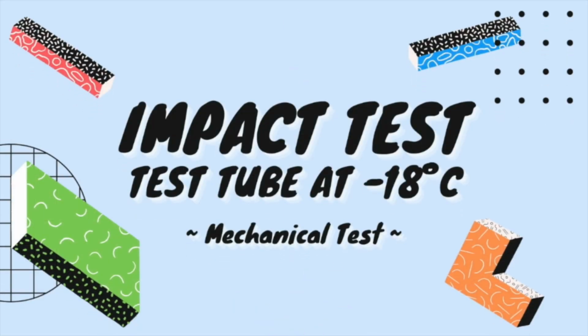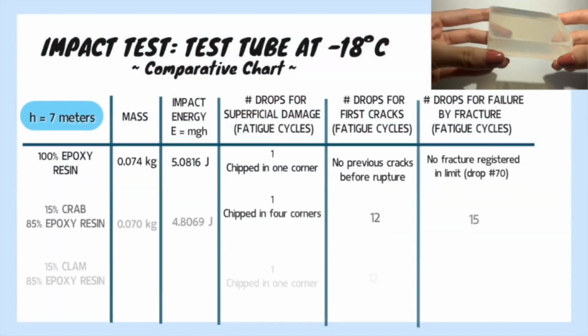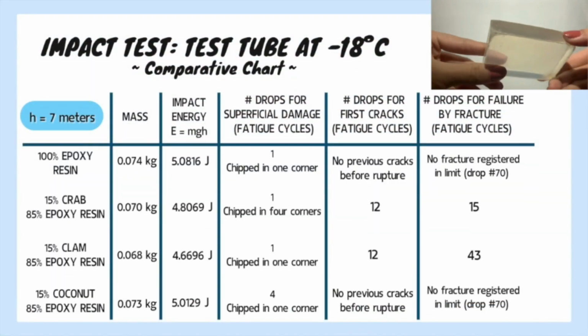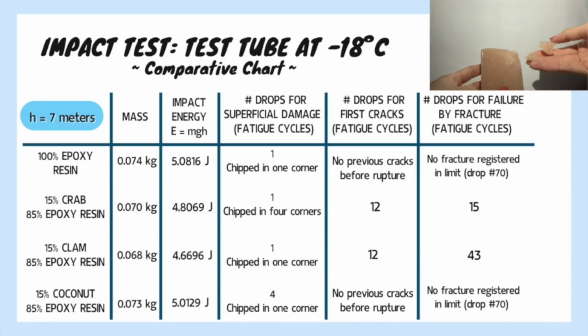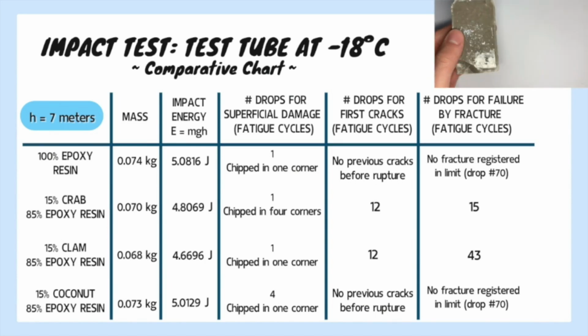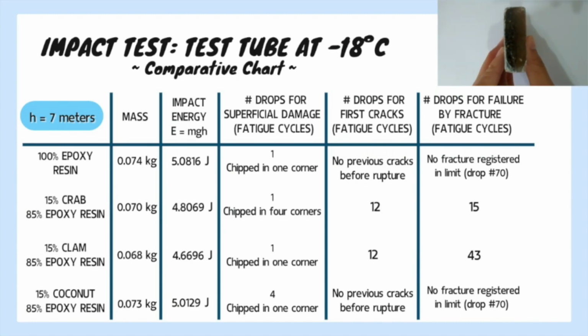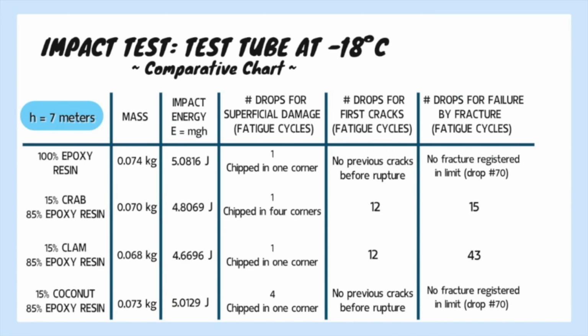Impact test at -18°C. The same impact test was repeated with test tubes previously exposed for 12 hours in the freezer. All the test tubes experienced greater resistance to impact under this condition. However, the pure resin was still better than the composites. The coconut reached the maximum of drops, but it had more damage than the pure resin.